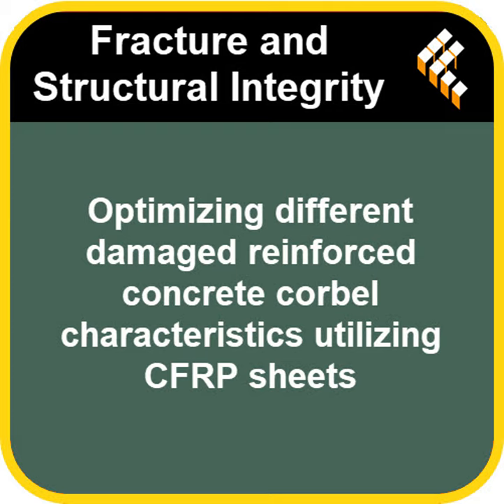Right, that gradual failure thing. Exactly. It also informs crucial decisions about when to intervene. That 50% damage threshold is a practical guideline. Repairing early is far more effective. So better timing for repairs. Yes. And it helps refine how to apply the strengthening, showing that side wrapping offers more benefits in these cases. All this leads to safer structures that fail more predictably if overloaded.